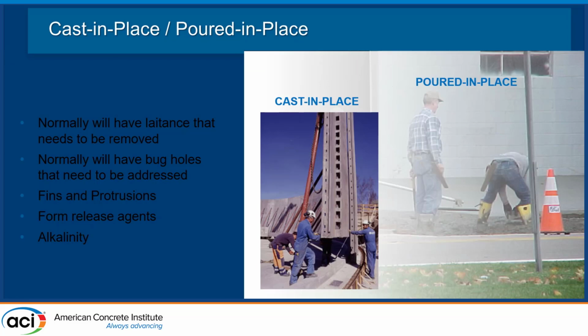Okay. So just some considerations when we're talking about cast in place or poured in place concrete, some of the things that need to be addressed before coating. Normally any poured in place concrete is going to have laitance on the surface, and that's the layer of unreacted cement paste that has a very low tensile strength, and it has very poor adhesion, and if you put a coating on there, it can actually cause failure down the road. And then we're also going to have bug holes that need to be addressed, fins and protrusions, form release agents, and then also the pH has to be addressed.